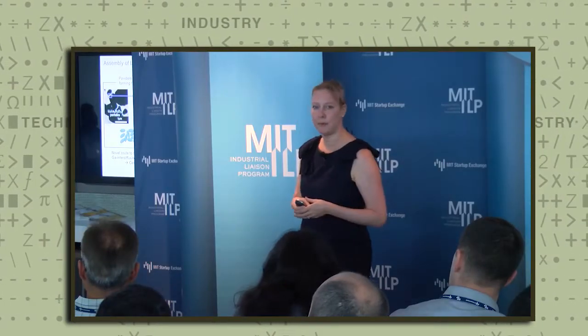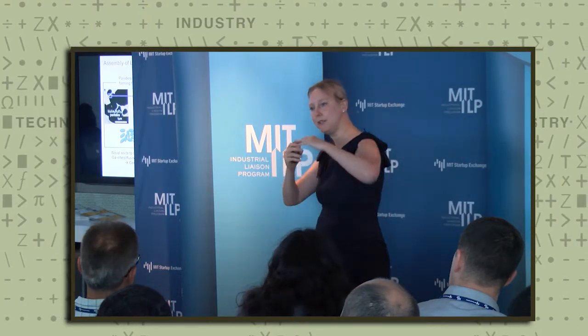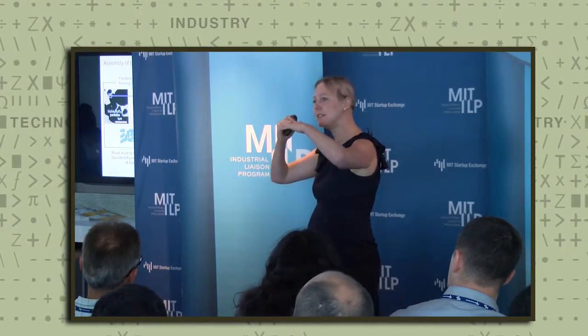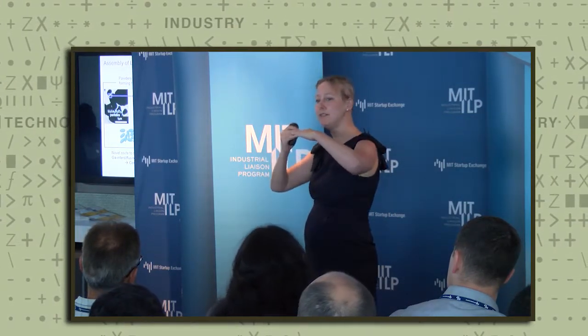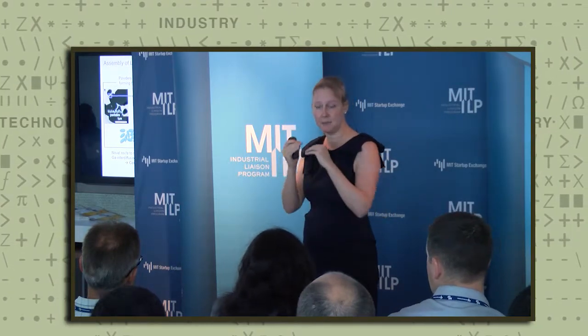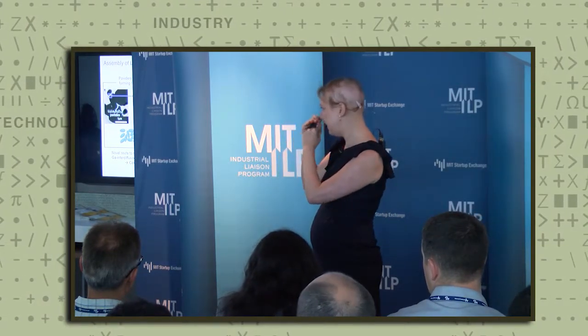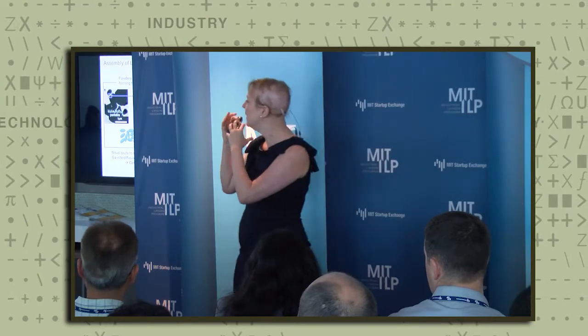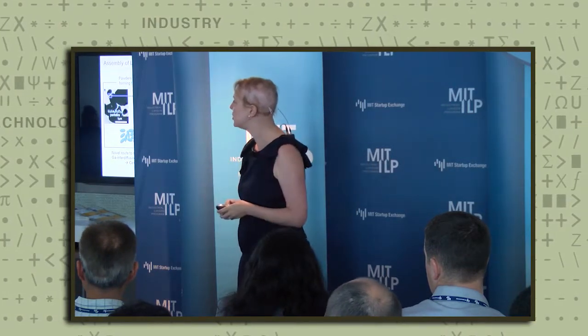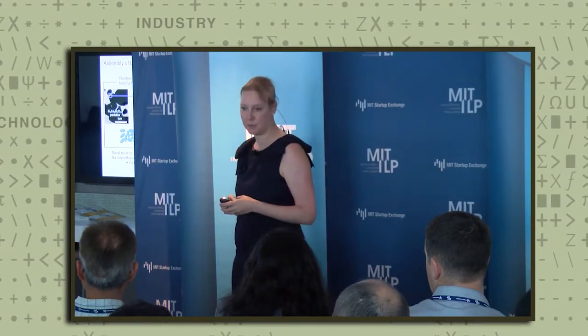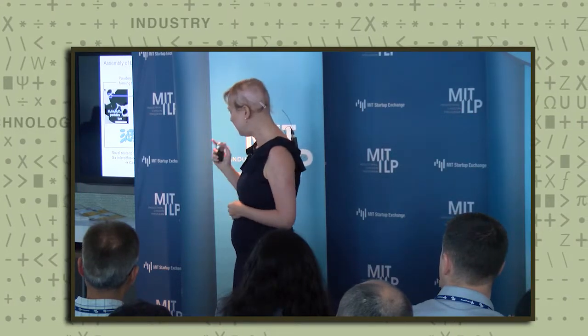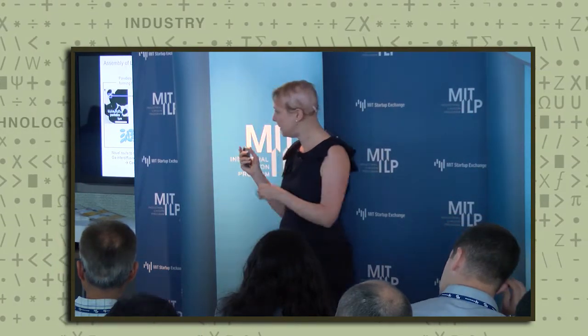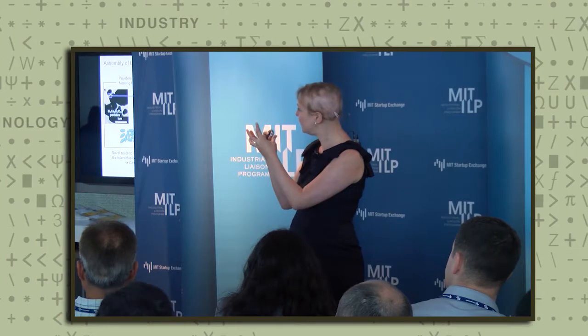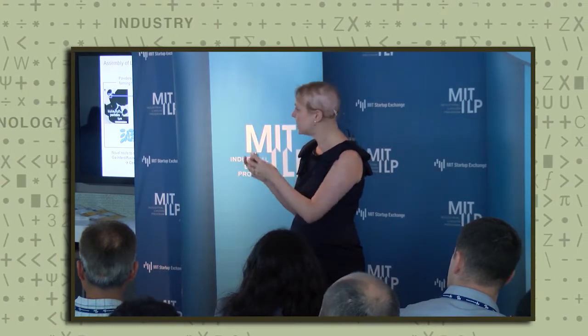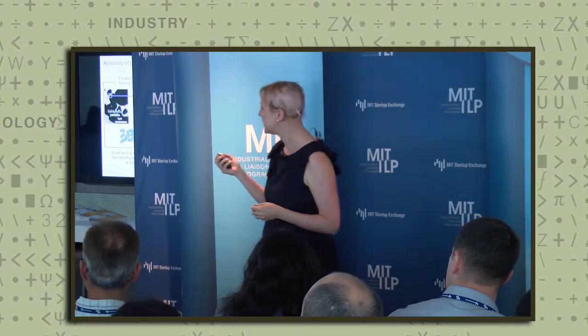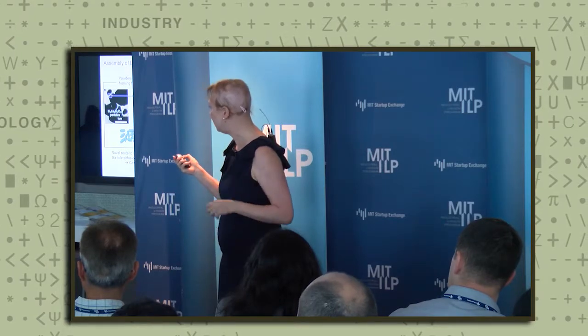Well, why is that important? That is very important because later when you assemble the battery cell and you bring in, for instance, an electrode, many of the different oxide anodes or other cathode materials are simply limited in making good bonds with this electrolyte, as to go actually to lower temperatures of about 900 or 1000 degrees Celsius. And this is one of the first assembly strategies here in the field for that material that we can use to create the electrolyte at a lowered sintering temperature to make the ceramics to come to such full assemblies.